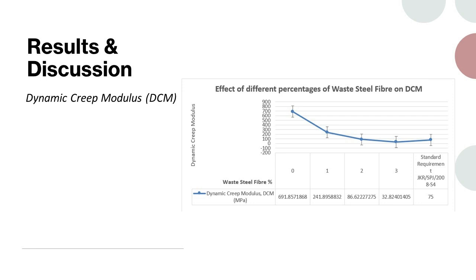DCM is a crucial parameter that reflects an asphalt mixture's resistance to deformation under dynamic loading conditions. The DCM value demonstrates the relationship between WSF contents and the dynamic stiffness of asphalt mixture. In the context of the provided data, as the WSF content increased from 0 to 3%, the DCM values decreased. The graph in the figure illustrates how the DCM value decreased as the percentage of waste steel fiber increased, highlighting the trend of reducing rutting resistance with increasing fiber content.